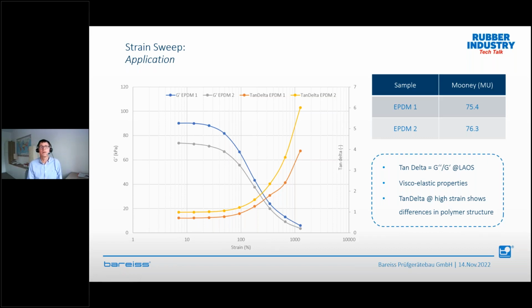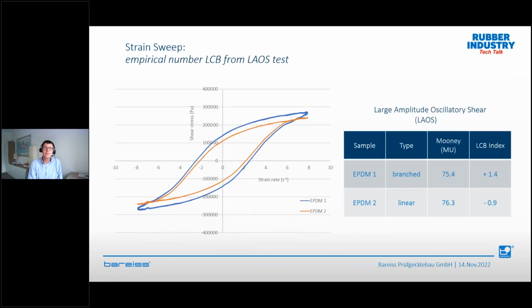So if you have such an instrument, and that is what the RPA Ultra can perform very nicely, you can run a frequency sweep and check tan delta at low frequency, at low shear rate, and check the tan delta at a very high strain value. And then you already have nice information about this. And for sure, we also can plot these very nice curves with our RPA Ultra. And you see the blue one has this broad character, which is a branched polymer. And you see the orange one, which has nearly secondary loops, and this is a linear one. And you see this in the LCB index. One is -0.9 and the other one is +1.4. So you have differences in branching.